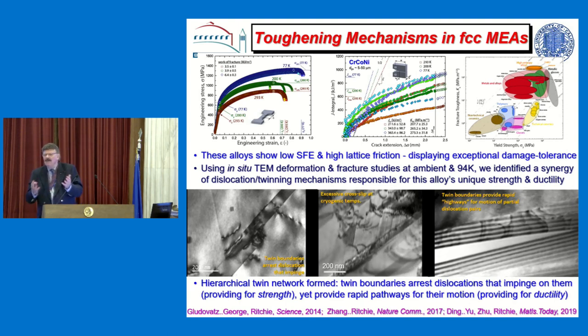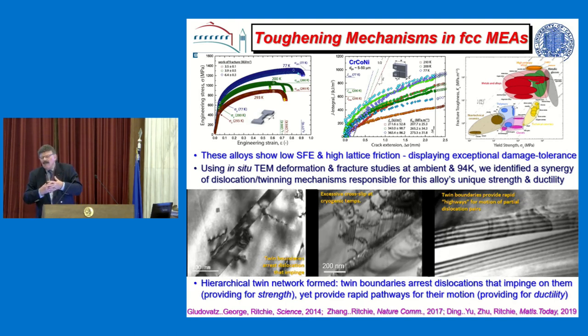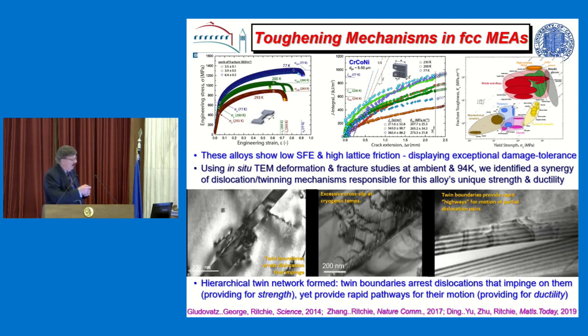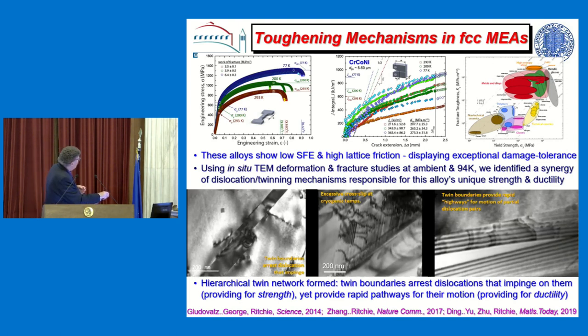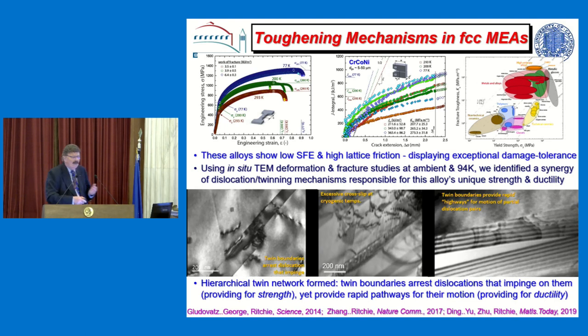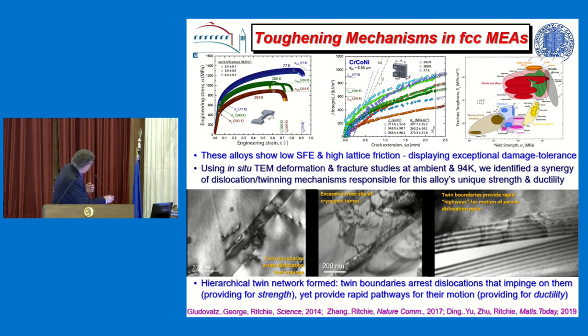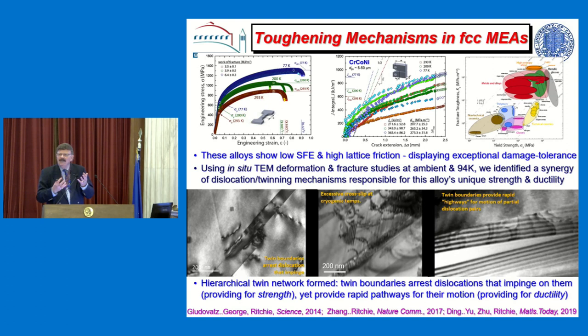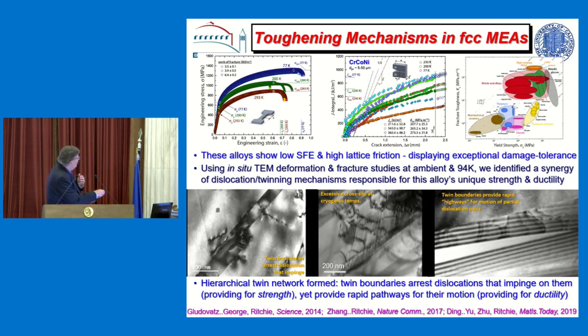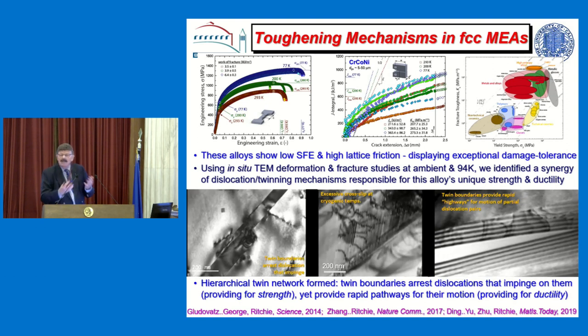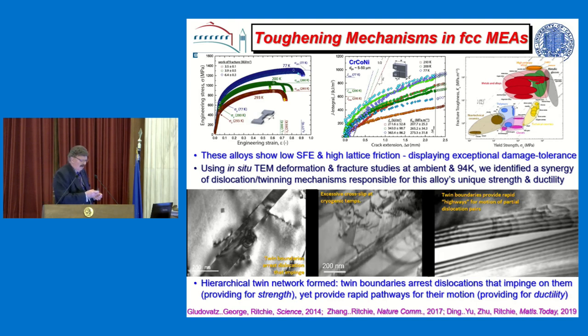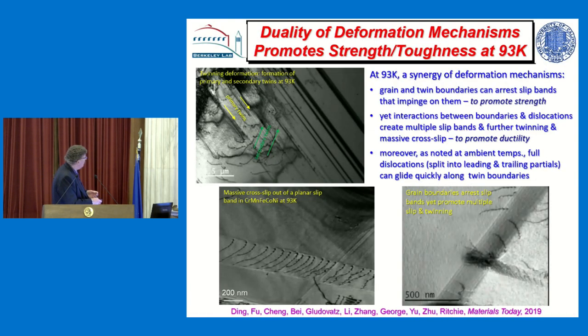And that's often difficult to do, but the combination is toughness. So these materials have these tremendous strain hardening regions, which harden the material, but this is the point when it basically fails by necking, so it delays the onset of fracture. So we've got a good combination of properties.